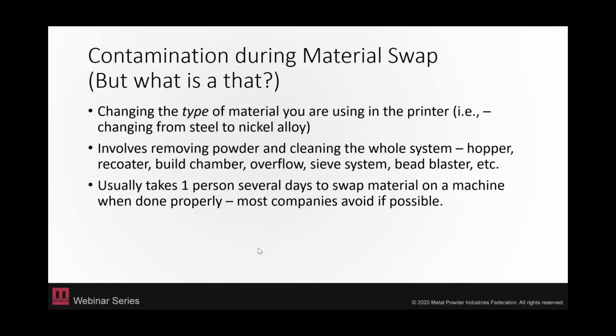So another source of contamination besides the process itself is material swapping. So that's when you're actually changing the type of material you're using. So for example, going from a steel to a nickel alloy. So it involves removing all the powder from the system, cleaning everything: hopper, coater, build chamber, overflow, sieve system. And for us, it usually takes one person several days, usually a whole working week, to swap the material on the machine when done properly.